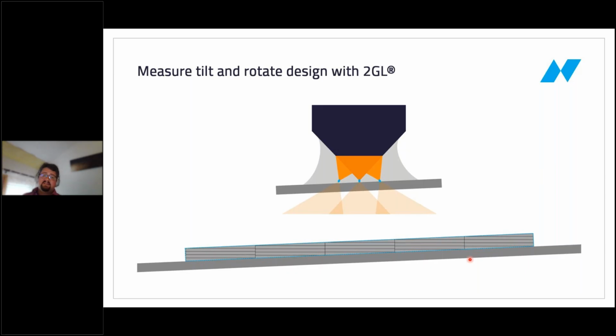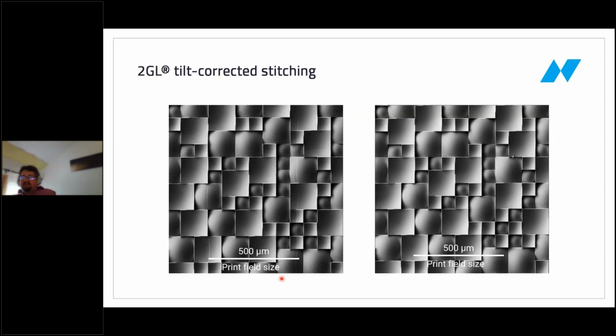But if you combine this tilt correction, rotation, and then you combine this with two-photon grayscale, you can actually get a smooth representation of the original surface, perfectly parallel to the underlying substrate, and you basically get the best of both worlds, and you get a correct representation of your structure, even with a slightly tilted surface. And we have tested this and implemented this for the customers. And here you can just see one example. This is a multi-lens array with concave and convex lenses of different sizes.